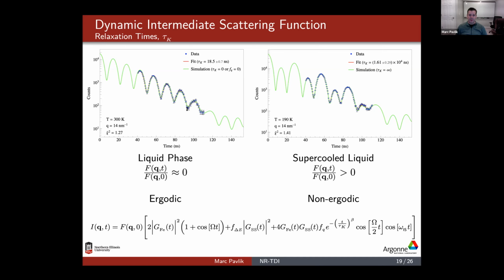Here we want to look at what happens when we have a small relaxation time, which indicates a fast relaxation rate. When I do that, you can see the high-low beat pattern is being washed away. This is like that room temperature measurement that we saw in the beginning. What is happening is the intermediate scattering function, again, goes to approximately 0, so this term of the equation is being eliminated. It can do that in 2 ways. If I'm using the KWW equation, I can either take this non-ergodicity term or this f_Q factor and make it 0, or I can make the relaxation time 0. Either one